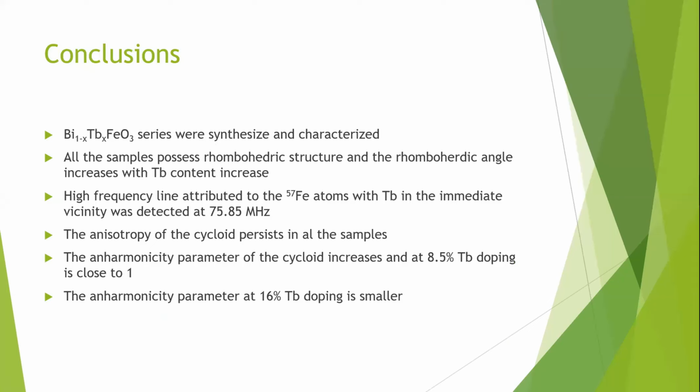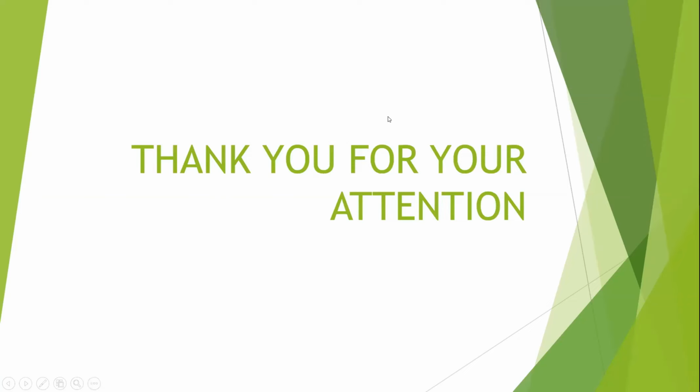The main conclusions are the synthesis of the series, the rhombohedral structure, the presence of the spatial spin modulated structure in all the series, and the anharmonicity parameter of the cycloids at 8.5% terbium doping is maximum, while at further terbium doping, it tends to be a little smaller. That's all. Thank you for your attention.